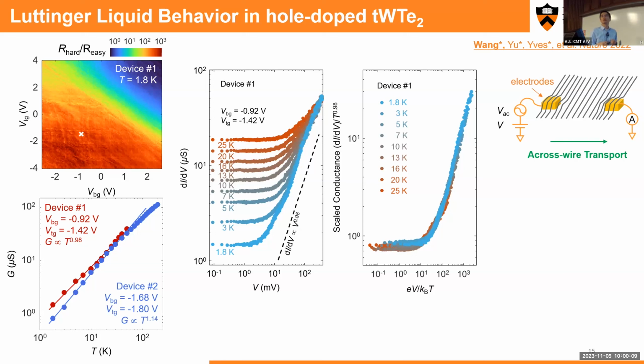And one more point that I want to point out, distinct from most of the previous results, for example, in the carbon nanotube or in the fractional quantum Hall modes for the tunneling, is that if you just cross this line here and this low bias line here, you get a crossing point somewhere here, which means that the eV over kBT, the energy scale number here, is not unitary. It's actually some number between 10 to 100, or I would say if we extract here, it's around 30, 40.